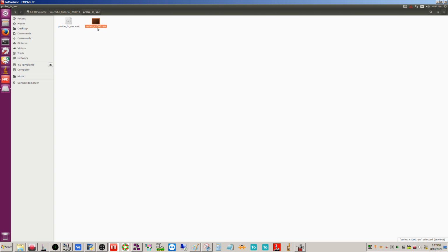If I import this into ImageJ, I can actually use this to calculate the incident probe intensity, by importing this and then doing an average of these 1,000 images. Then if I sum up each pixel in the DP from that average, I end up with the total probe intensity. The reason that's useful is I can use that to very quickly calculate what are called quantitative STEM images.